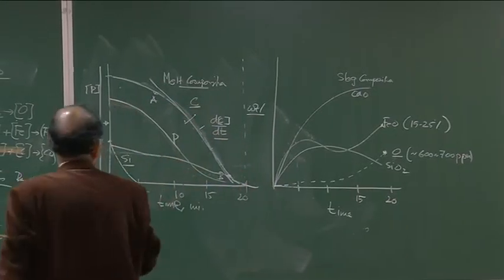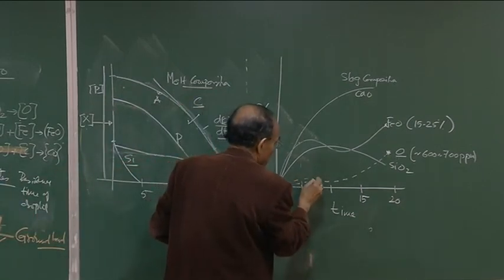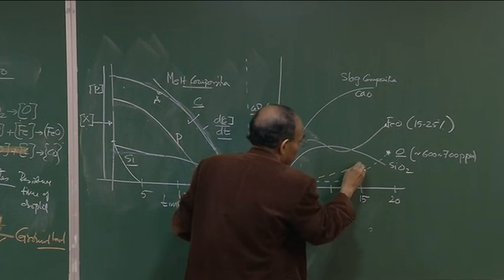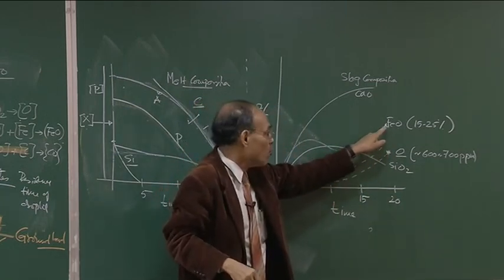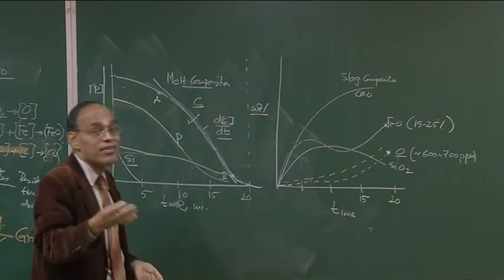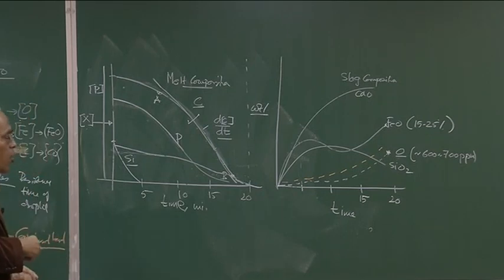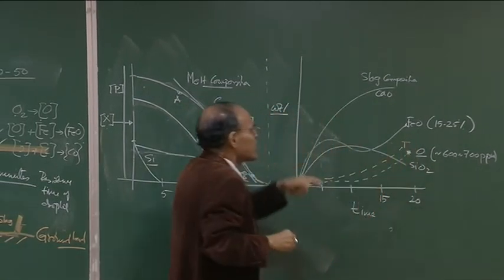As I have indicated, if my temperature also increases like this, following the bath, then with the increase of FeO the temperature is going to be increasing, and as a result there is a great danger of phosphorus reversion from the slag itself. These are all schematic values.